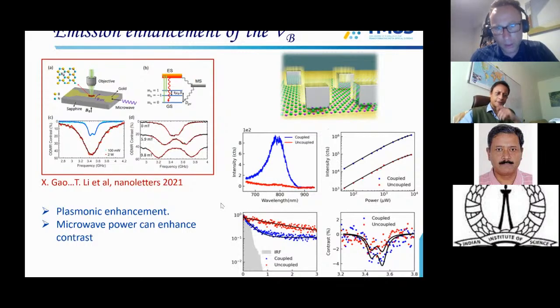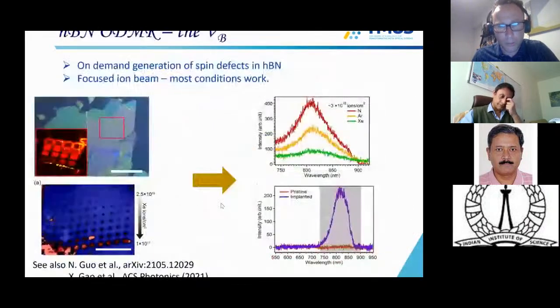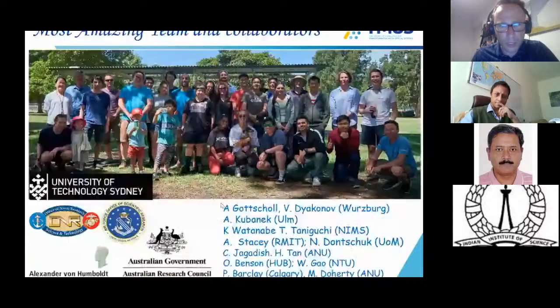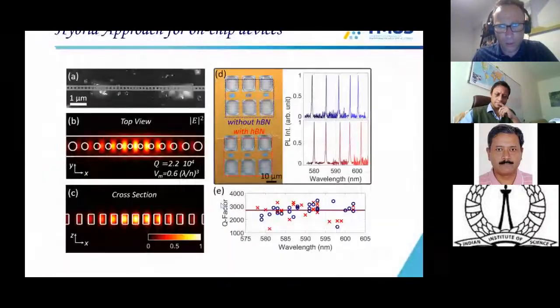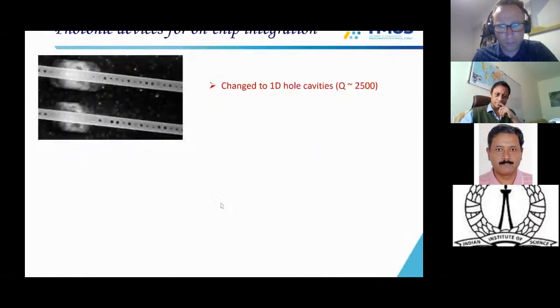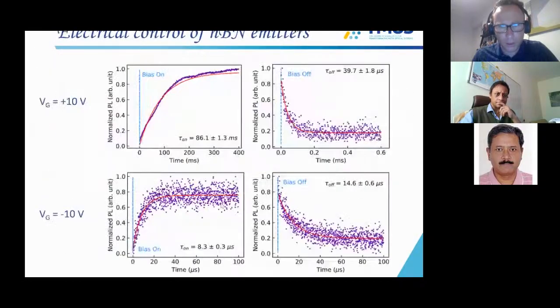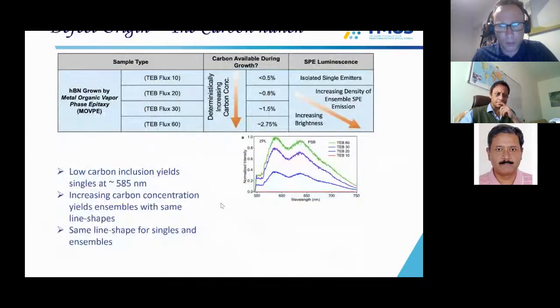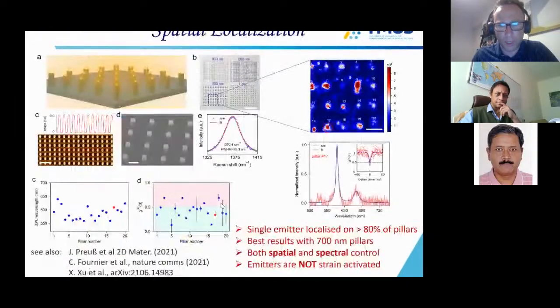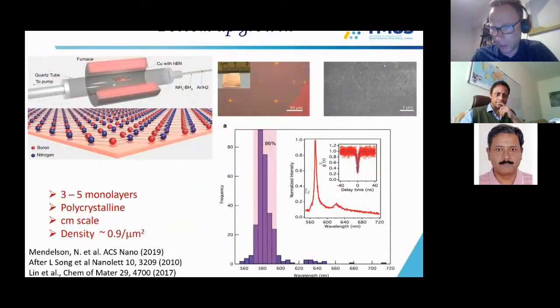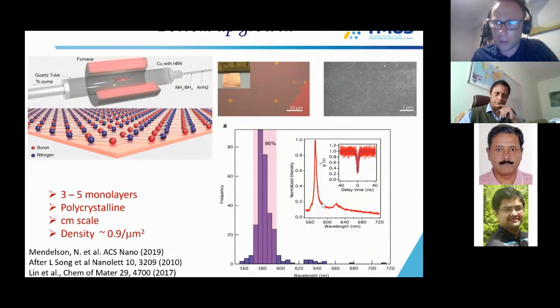So, the brightest emitters. In the lab, for the single emitters, we can measure routinely about 2 to 3 million counts per second. Those typical emitters here, we can measure about 2 million counts per second, so that's 2 times 10 to the power of 6, and that's without any photonic structures. If you use a photonic structure like a solid immersion lens or a cavity, you can get up to 10 million. So they're very bright.